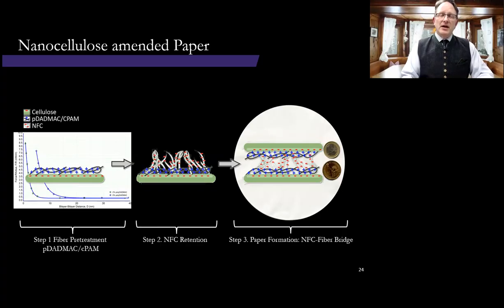Just a comment about papermaking. Retention of fine nanoscale materials such as NFC is very problematic in papermaking. And so papermakers utilize a retention chemistry in order to capture those nanomaterials and be able to take advantage of their properties. To accomplish this, in this first step, we take the wood fibers and pre-treat them to adjust the conductivity and the surface charge. What I used was a chemical, polyDADMAC. What polyDADMAC does is compress the electrostatic double layer on the surface. And then it allows our cationic polyacrylamide, which is our retention aid, rather than laying flat on the fiber, to create a net or a web that can capture the nanofibrillary cellulose fibers in this step here. What that allows is an NFC fiber bridging mechanism between wood fibers and the nanofibrillary cellulose fibers.